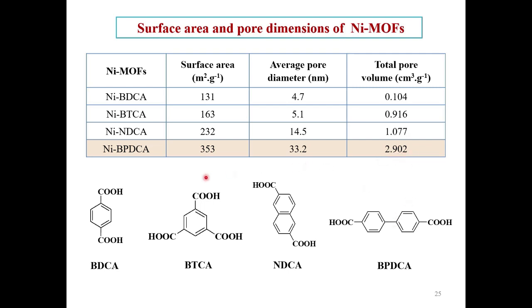This is the structure of the different organic linkers and how this BPDCA is effective because of this structure, suggesting that a biphenyl ring is there, and carboxylic acids are attached to the tip of each biphenyl ring. Here the fused ring is there, here is only a single phenyl ring, here again a single phenyl ring, and because of the structural stability of that BPDCA, it gives more stable, higher surface area with a very impressive average pore diameter and total pore volume of the nickel BPDCA metal organic framework.